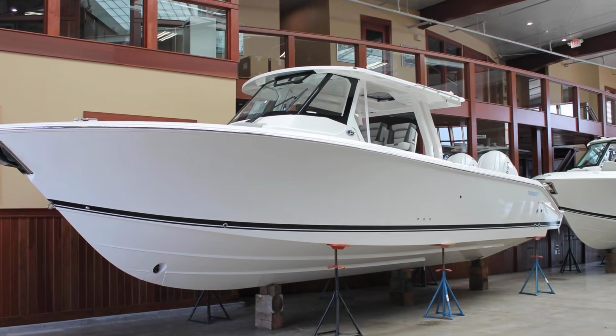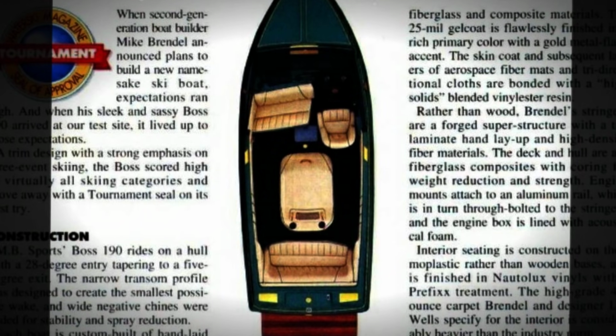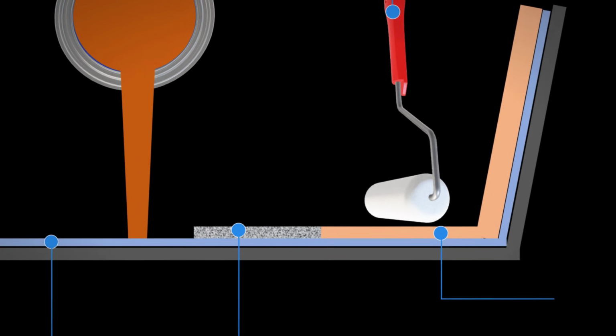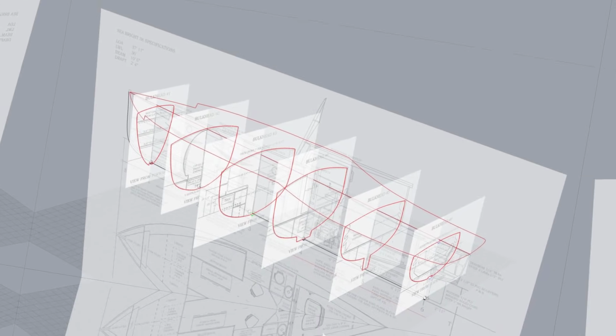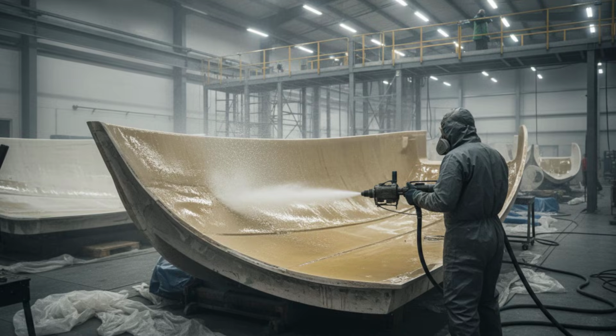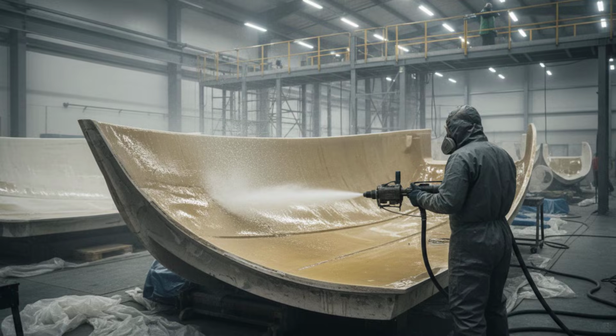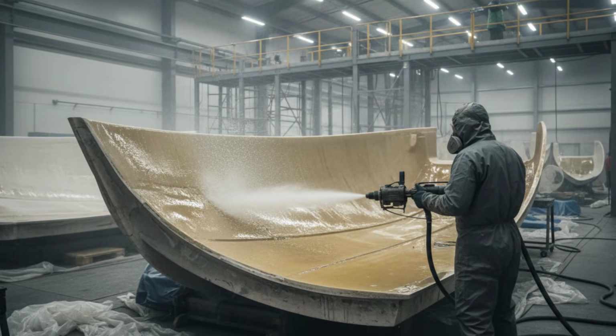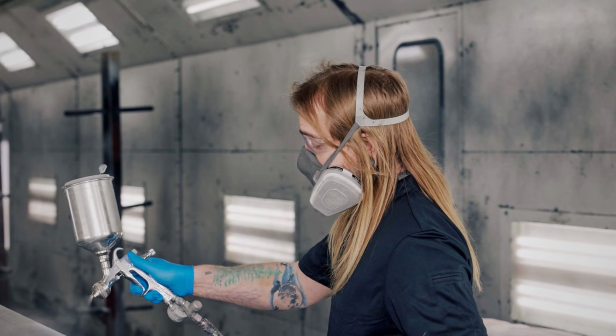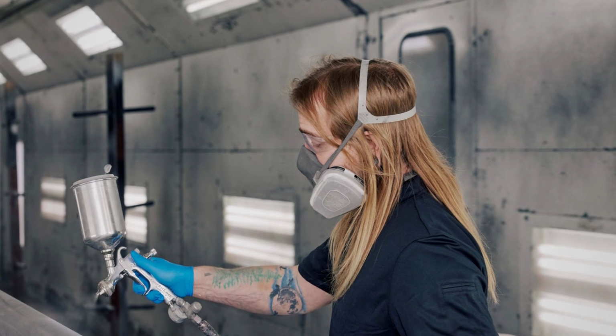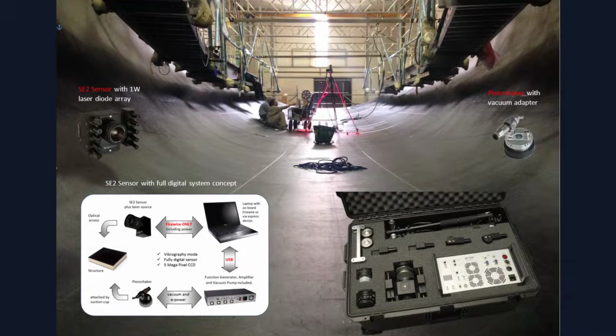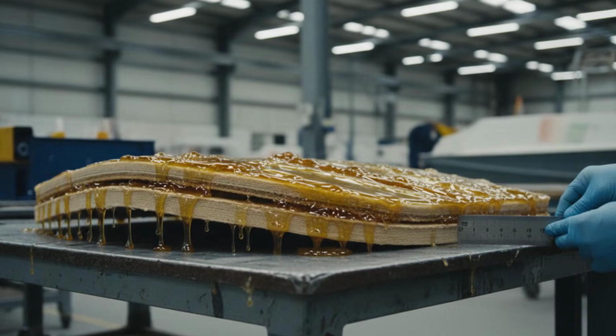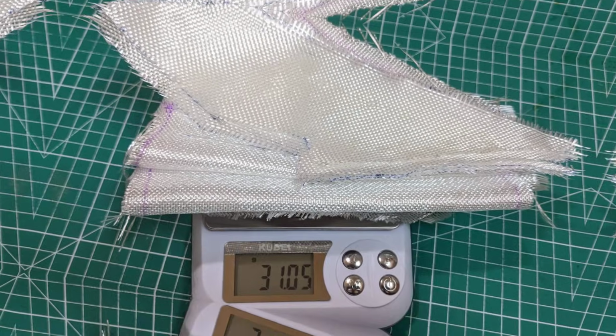This is the most common approach in this price range, and it's where the marketing gets deceptive. A builder can call a boat hand-laid if just 1 structural layer is placed by hand over a chopper gun base, and at the bottom, full chopper gun. A worker sprays randomly chopped 1 to 2 inch glass strands mixed with resin into the mold. The result depends almost entirely on operator skill. Thickness varies, strength varies, air pockets form, and the finished laminate carries excess resin that adds weight without adding strength.